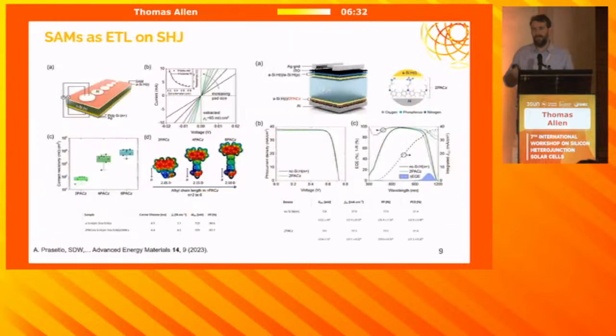Okay, so now I'll just shift gears a little bit. So now this is just on silicon. This is SAMs, the same 2PACz SAM as an ETL on silicon heterojunction cells. Here, Adi, my PhD student, did some great work where the idea is that the SAM is now anchored not to the ITO and pointing towards the absorber. It's anchored to the absorber, which is now silicon, and it's pointing towards the contact, and that changes the direction of the dipole. So instead of collecting holes, we're now collecting electrons in the silicon.